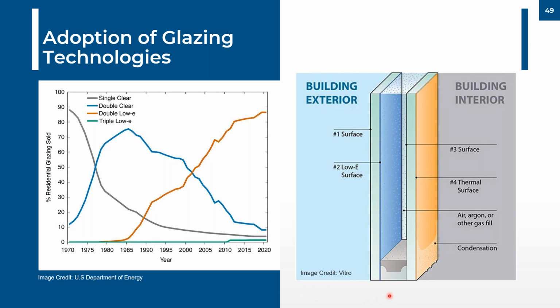But most of the time, for code compliance today, we've been able to satisfy code with dual pane insulated glass that has low E coatings applied to it, argon fill, and the various low E coatings. Most recently, we've seen low E coatings applied to surface 2. This is the room side facing surface of the outside sheet of glass. And now we see some low E coatings applied to surface 4. So this is now the interior facing surface of the glass, a low E coating applied to the inside surface. You can touch it, you can clean that low E coating.